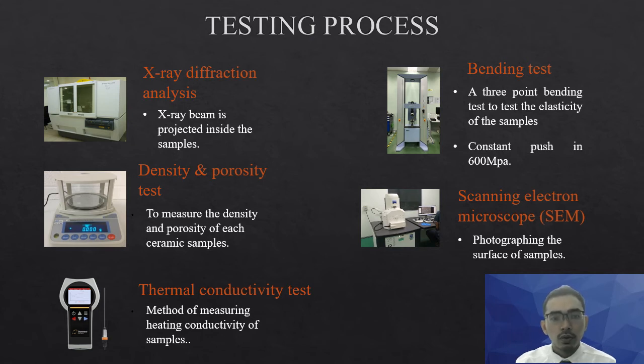Now we will proceed with the testing process. The first testing is the X-ray diffraction analysis, or XRD test. The X-ray beam will be projected onto the sample to determine the crystalline structure of each sample. Next will be the density and porosity test. It is to measure the density and porosity of each ceramic sample. The sample is immersed inside a beaker of distilled water and kept for a period of time.